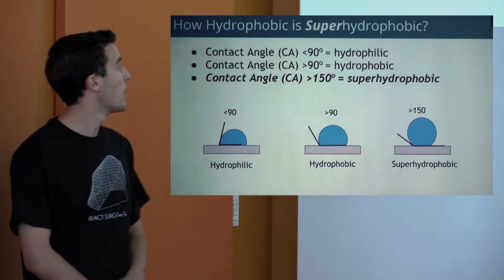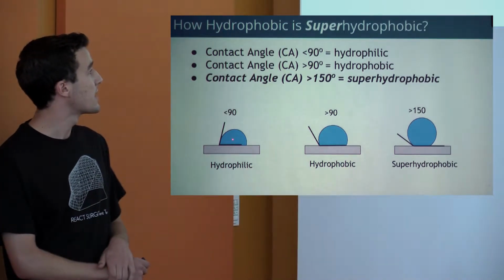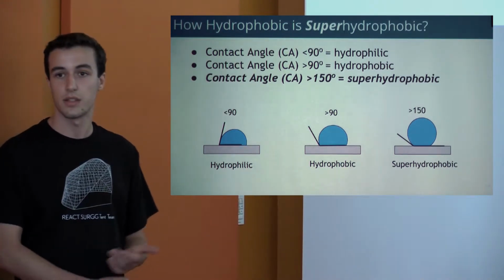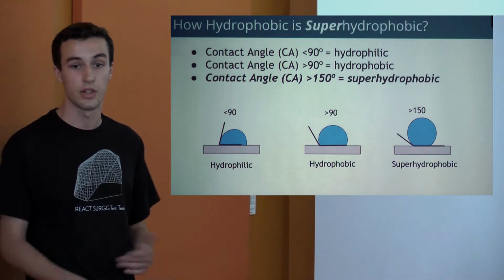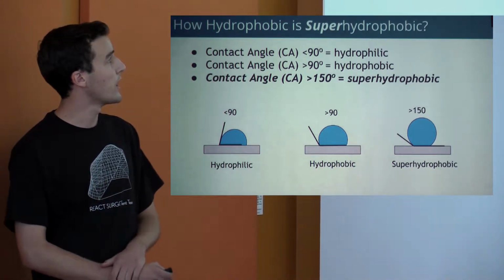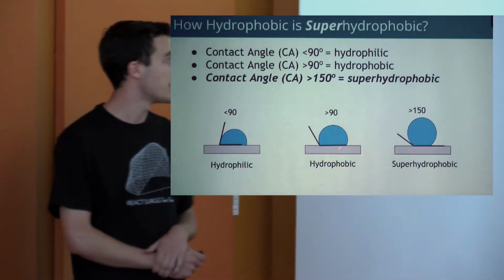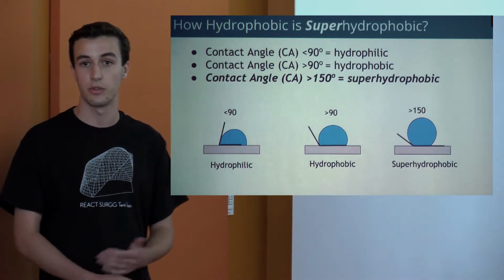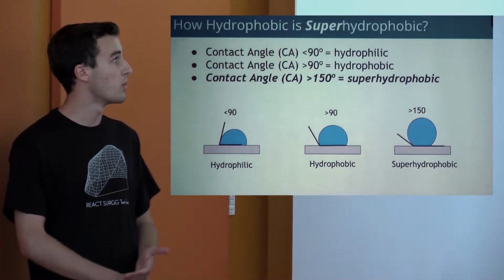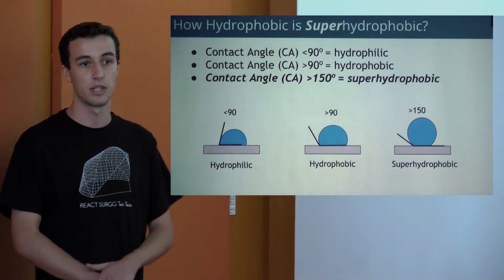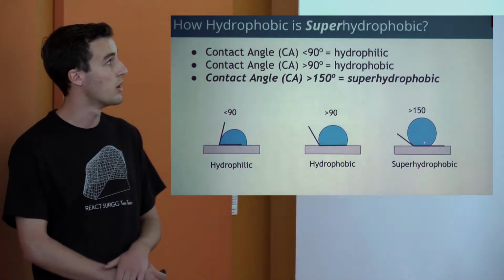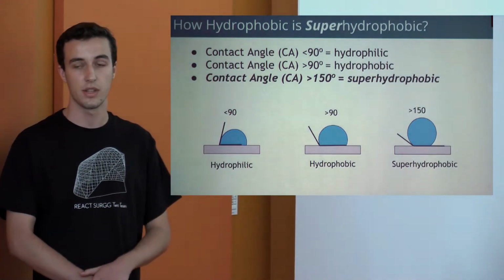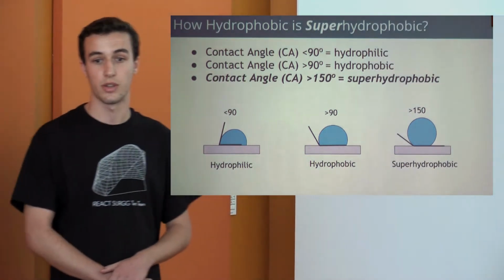So for instance, for a contact angle of less than 90, the surface is hydrophilic, meaning that the surface likes water and it isn't good for our needs. For a contact angle greater than 90, it means the surface is hydrophobic or repels the water. But what we really wanted to achieve was a superhydrophobic surface with a contact angle greater than 150 degrees. So that was one of our goals with our surface.